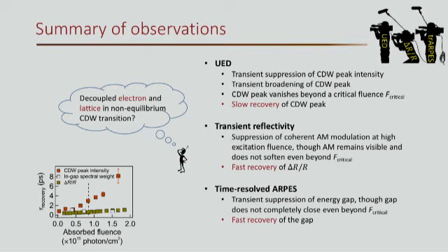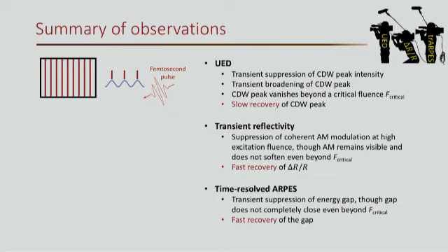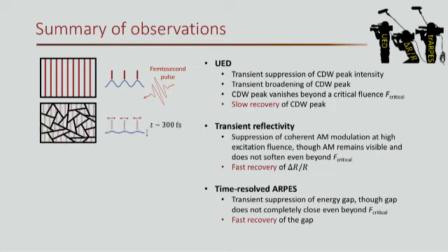So what could be the picture here? To combine all these observations together, here is what we think really happens. First of all, you have a long-range order of charge density wave throughout the material, represented by these red bars representing charge modulations. This is a cartoon picture of electron density modulations. Then you pump with the ultrafast light. What happens first is, as we see, a broadening effect of the UED peak. It creates a lot of small domains. Concomitantly, there is a suppression in amplitude, represented by a lighter color of these charge density modulations. And again, we discussed the phase fluctuations, represented by this horizontal phase fluctuation, with amplitude fluctuations represented by these vertical arrows.